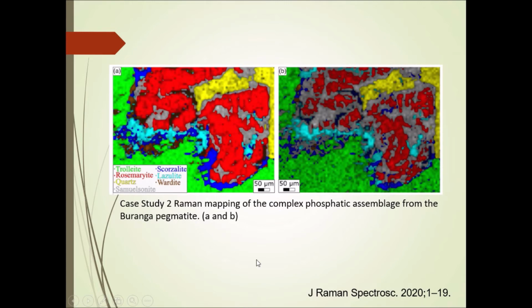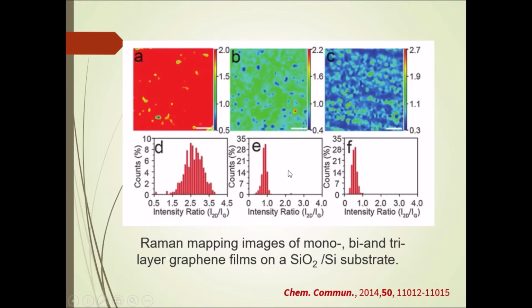One of the most important applications of our microscope, or Raman microspectroscopy in general, is mapping. With mapping, we can scan a very large area, from a few micrometers to millimeters, and we can identify if we have one compound or several compounds. Here we have a complex phosphatic sample, so each color represents a different structure or compound in the sample. So we can give each one a different color, and we map and have a general overview about the distribution of the sample.